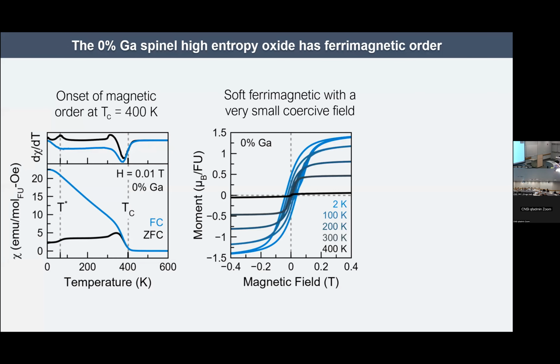And we didn't have to wait much longer to get a little bit more insight than that, because from magnetization measurements, we can see that our low temperature magnetization is saturating at just shy of 1.5 Bohr magnetons normalized per formula unit. But we know that a spinel formula unit has 3 transition metals. AB2O4 is the conventional formula. So that means that my 3 transition metals together are producing a saturated moment of only 1.4 Bohr magnetons.